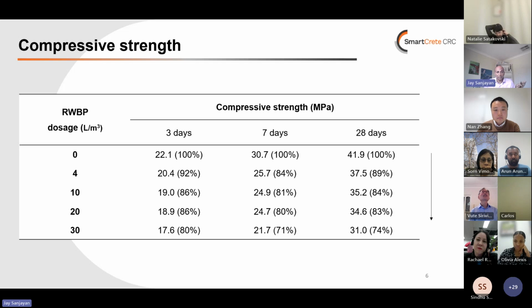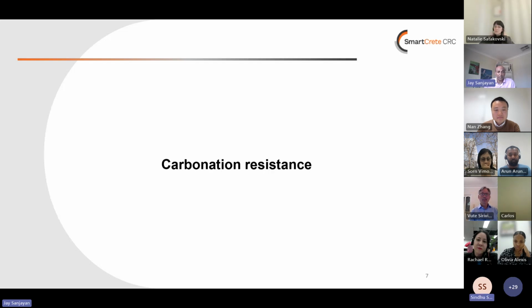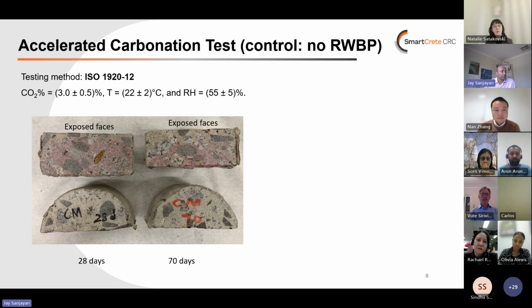But we put that issue on the side, and then let's go and look at carbonation, which is where the exciting results are going to come. What we did is accelerated carbonation test, following the international ISO standard. So basically we increased the carbon dioxide concentration in the chamber to about 3% with the temperature 22 degrees, relative humidity 55. And the controlled concrete, we get a 5 millimeter carbonation depth after 28 days.